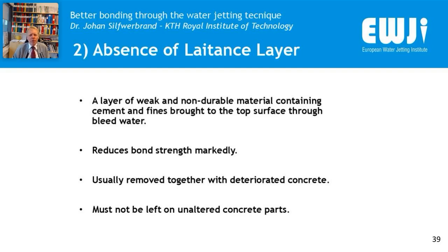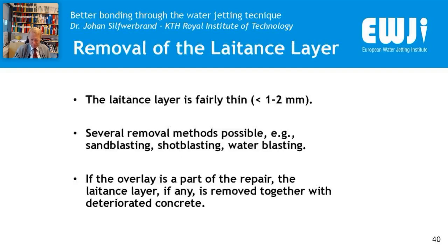It is a problem when you are making buildings and you are using precast hollow core slabs for buildings, for office buildings, for instance, or for apartment buildings, and then quite often you are putting an overlay on top of the hollow core slab to make an even surface. And then if you want to have bond in these cases, you need to at least sandblast or shot blast the precast slabs before casting the overlay. So this I have already said, I can skip that.